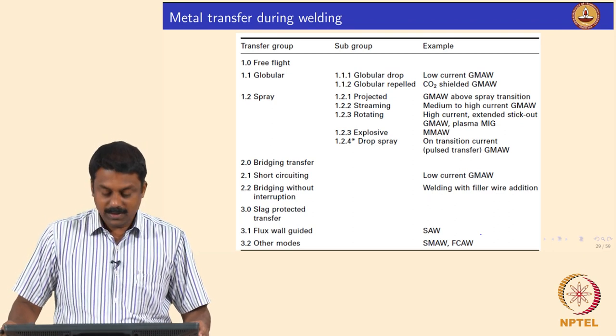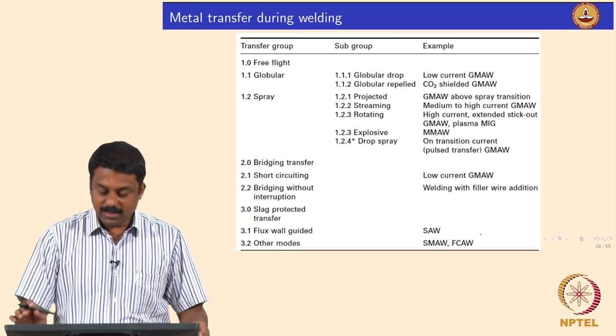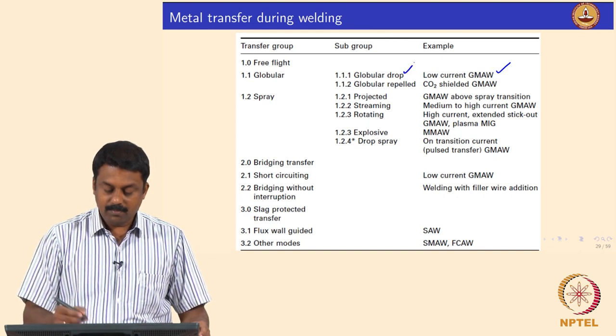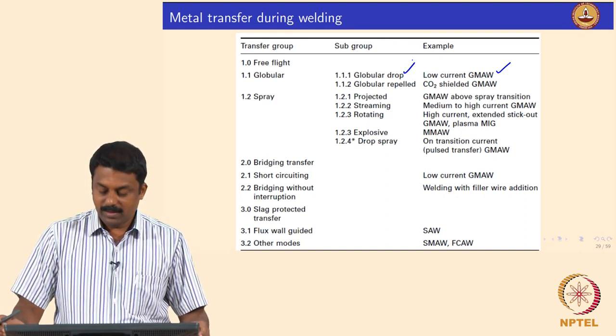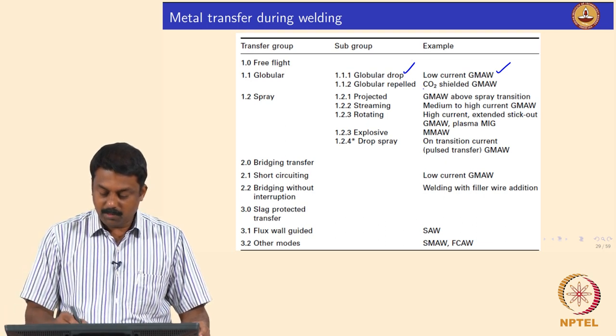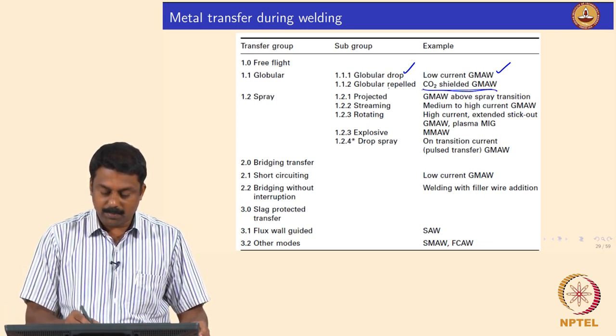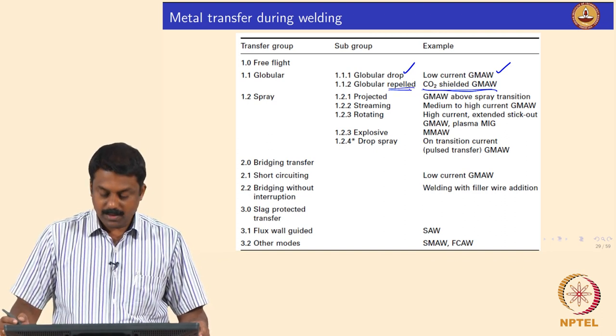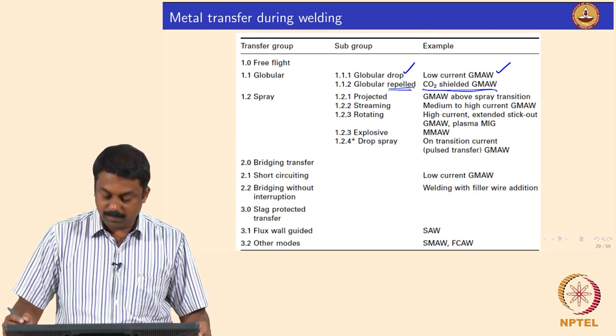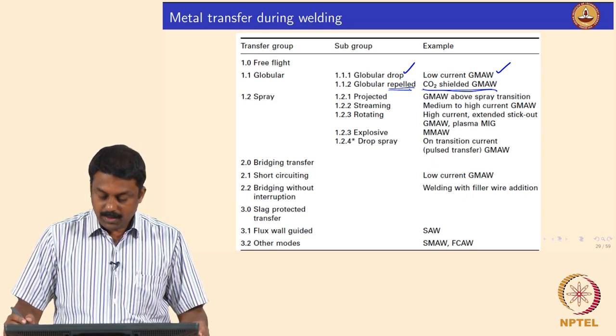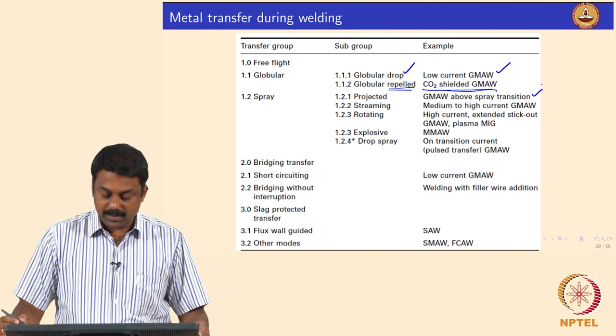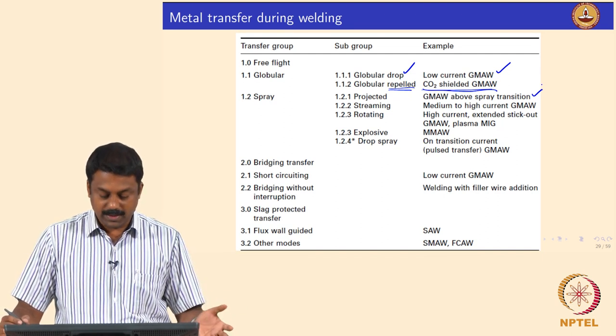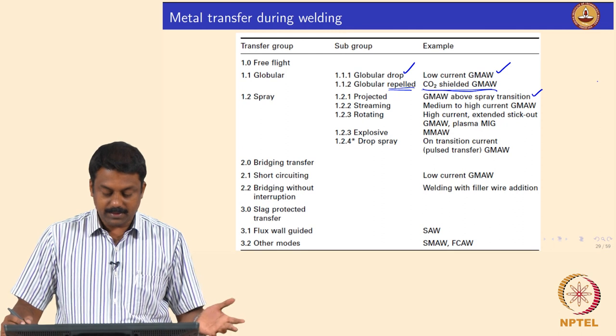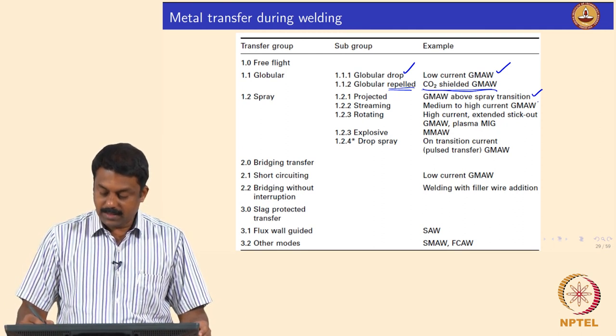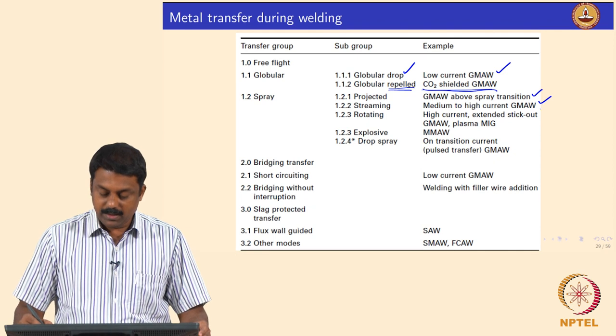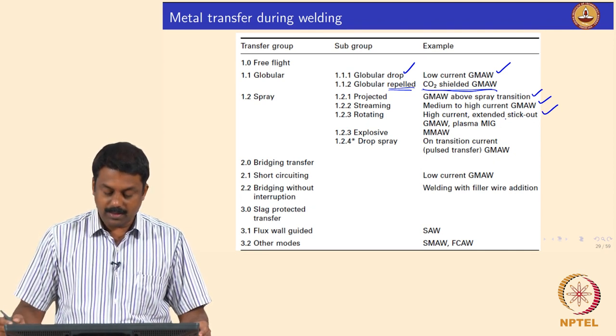So, what are the most commonly observed transfer modes in various applications? As I said, for low current GMAW, it is globular. In CO2 shielded GMAW, it is globular and repelled globular, because of the instability associated with CO2. Above the spray transition, it is the drop spray or projected spray, it is the same. And once you increase to high current, it becomes streaming, rotating and explosive transfer.